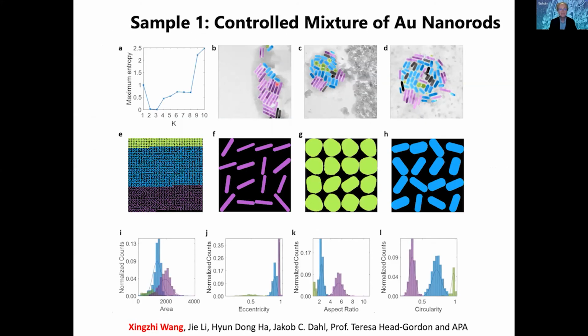So here's a sample where we've taken two sizes of nanorods and mixed them together, 50-50, and we've simply applied this algorithm to it. And it's an algorithm in which we want to minimize the entropy of the selection process. And you can see here that this particular algorithm did an approach where the absolute minimum says there are 3 different kinds of particles. That's a little bit better than if we say there are only 2.